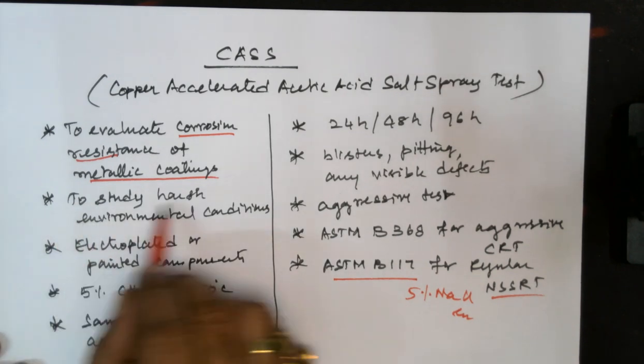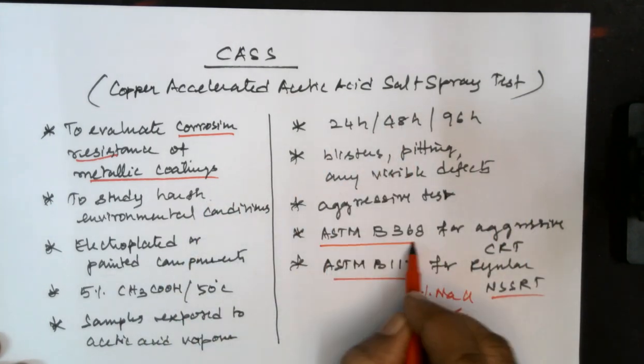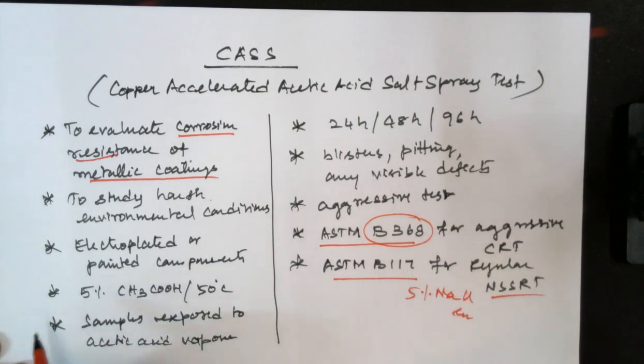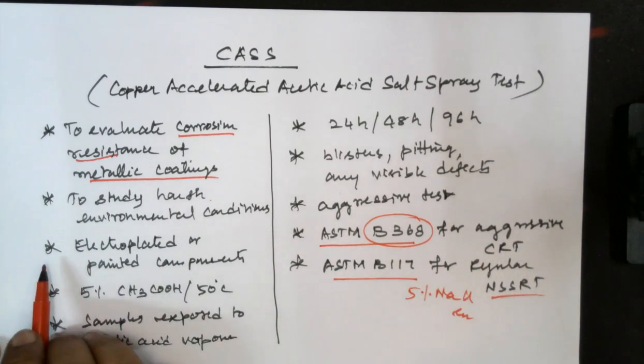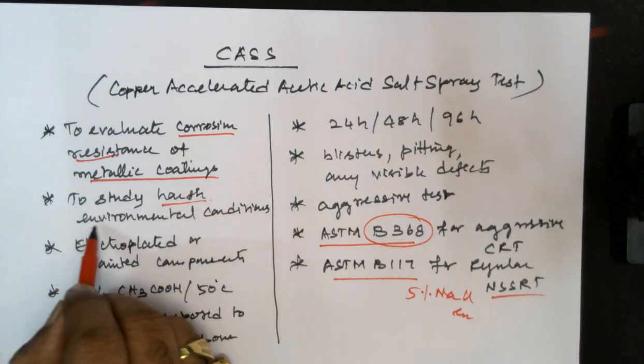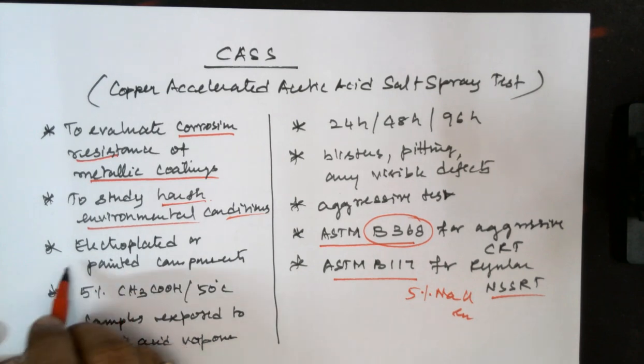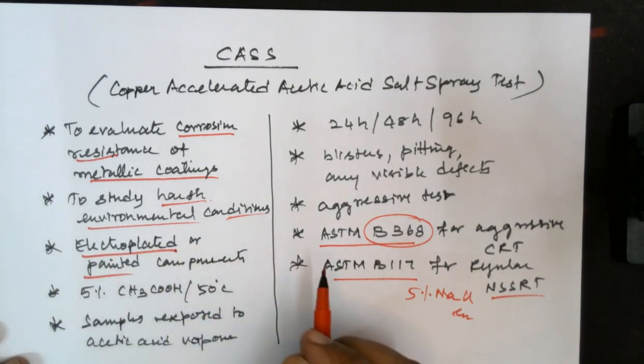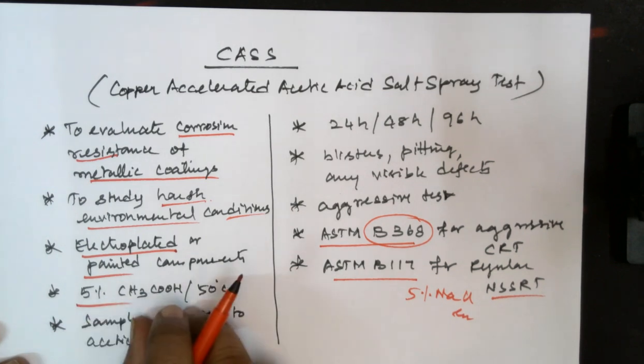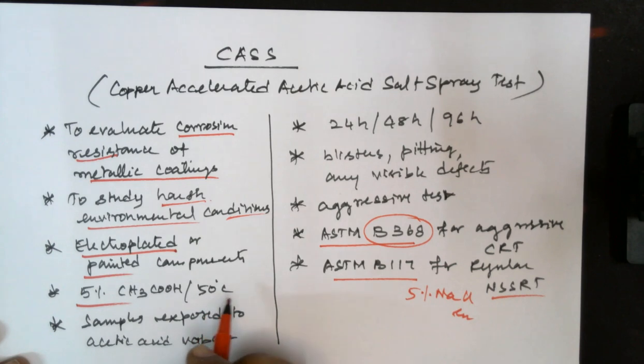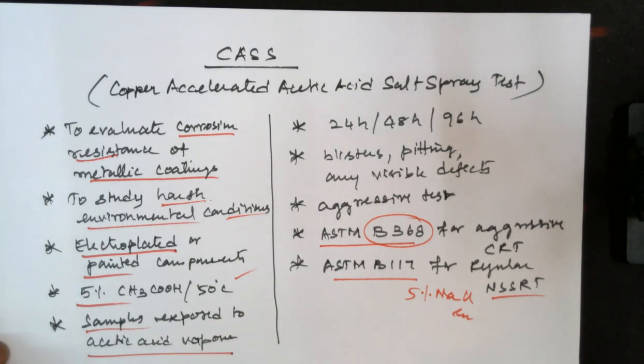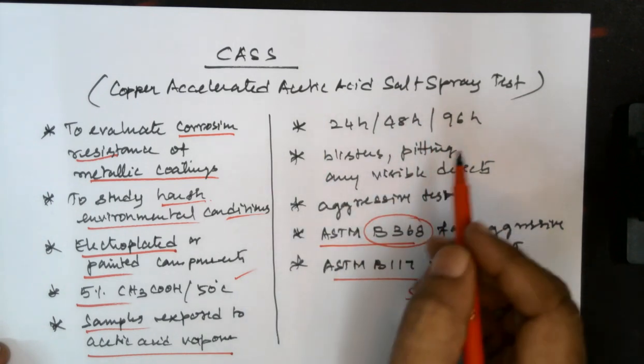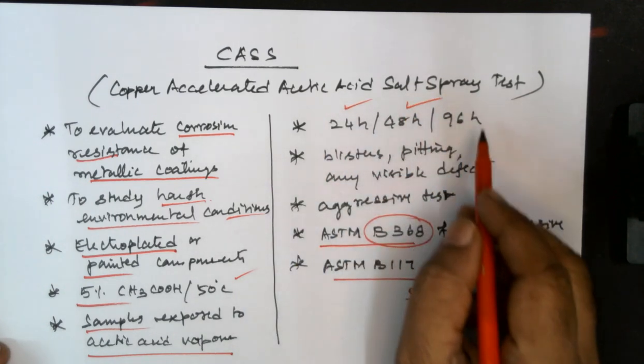And this ASTM B368 is also used to study, it's an aggressive corrosion resistance test, used to study the harsh environmental conditions of electroplated components or painted components. Usually we take a 5% acetic acid solution in a chamber that is kept at 50 degrees centigrade, and the samples coated with the relevant paint materials are exposed to acetic acid vapor. Normally, based on the customer requirements, it can be kept for 24 hours or 48 hours or 96 hours, etc.